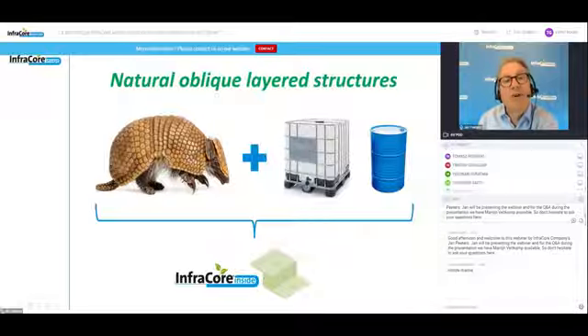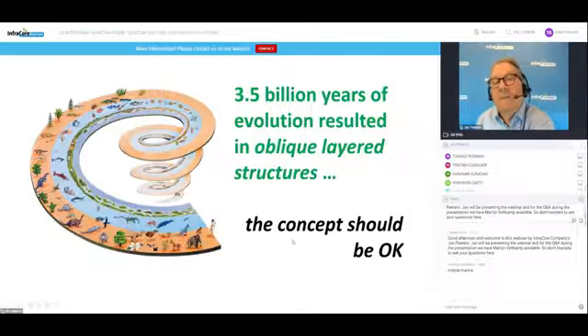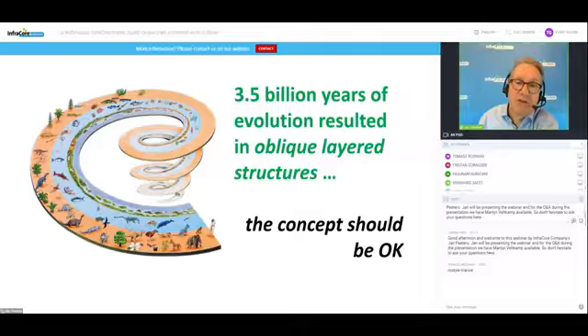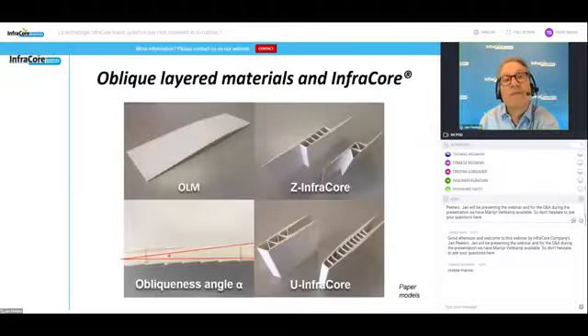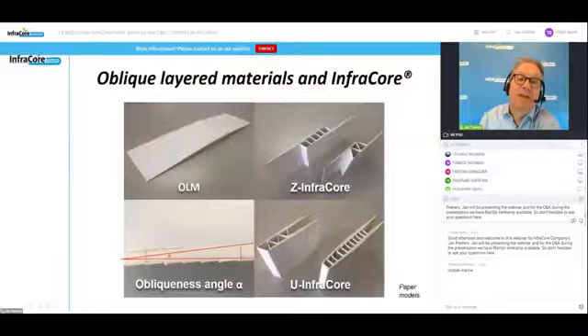And if you were to break open the connections by delamination, for instance, you still have the consistency of the base structure itself. So that is the damage robustness which we built into the structure. And what is a nice concept is that evolution came up after 3.5 billion years with oblique layered structure. So the basic concept should be okay, and that's what we're using. This is what it looks like, oblique layered materials in paper models. That's the skin. And there are two variants of the technology.